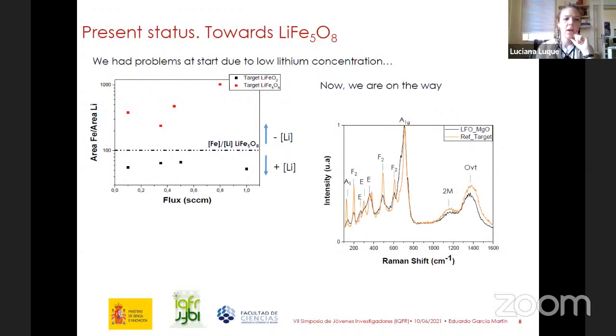Excuse me, you have 30 seconds left. Yes, finishing. Early on we had a problem with lithium concentration, but we are on the way. We explored a new stoichiometry in the target, which allowed us to have enough lithium in the material to develop the structure we want.